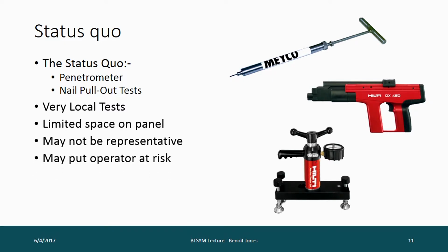And they might put the operator at risk. I've put that in because if you wanted to test the actual lining, it would put the operator at risk. And that's what we used to do. We used to just go up to the lining and do tests in the lining. But also, there are risks inherent in using this equipment. You've got explosive cartridges, you're firing nails, lots of potential accidents. They're also destructive tests to some degree on a very small scale, not if you're doing them in a panel that you're going to throw away, but if you're doing them in the lining. And they have quite poor repeatability. Even with a very good operator, you're talking plus or minus 30% repeatability.